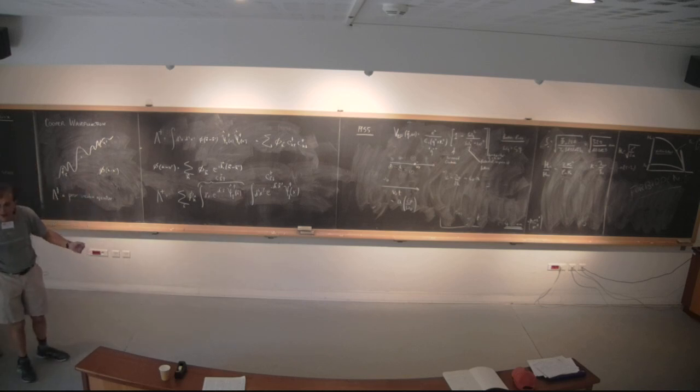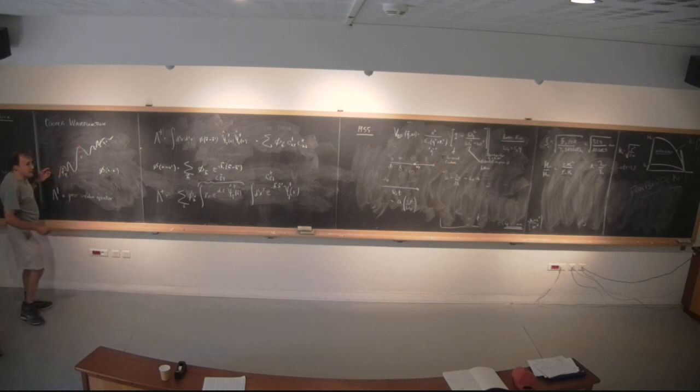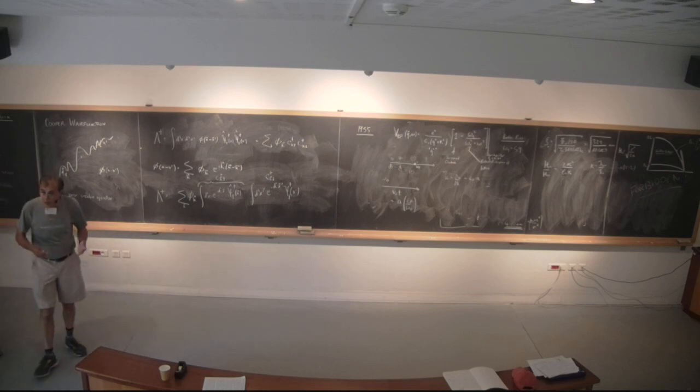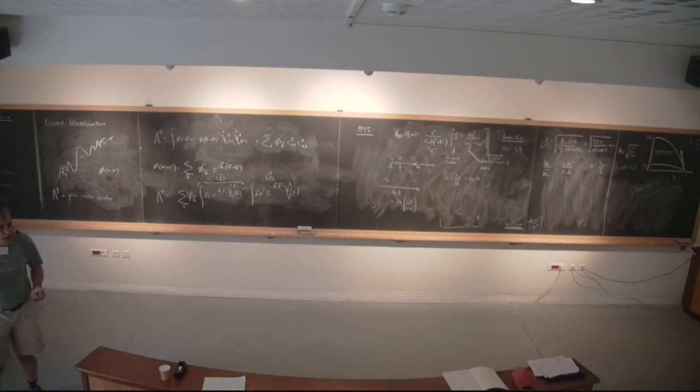Okay? They're an up, down, minus, down, up. So this is an entangled state, and it's going to be entangled over the coherence length. The coherence length of aluminum is something like half a micron. It's immense, okay? So that's entanglement over a long scale, and then we're going to make the entanglement even better